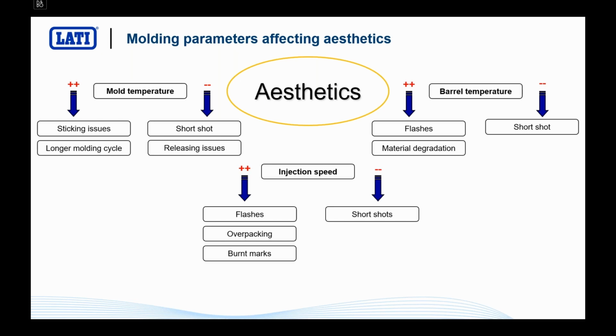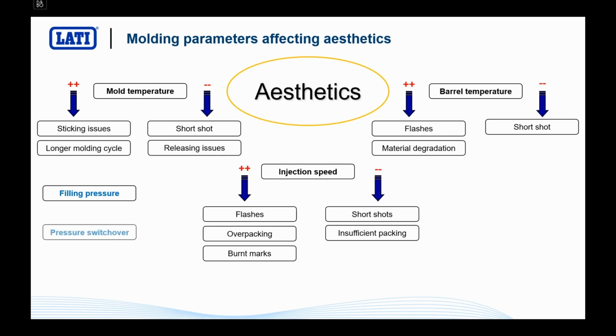If injection speed is too low, of course, you run the risk of having short shot or even having insufficient packing. I want to focus your attention on the fact that these three parameters are not the only ones actually affecting the aesthetic of your plastic. You also have the filling pressure, the switchover time, and the packing pressure. Packing is really very, very important. Packing is the pressure and the time that you apply when the cavity is full to properly pack the plastic polymer into the cavity.